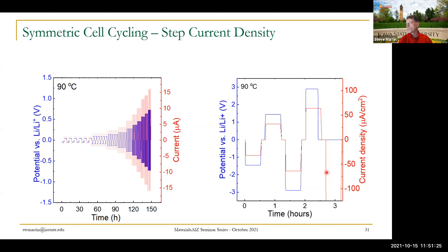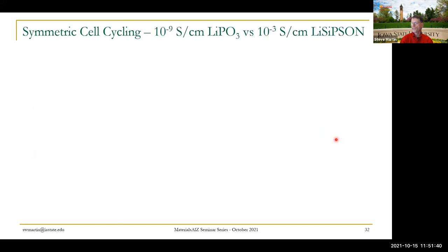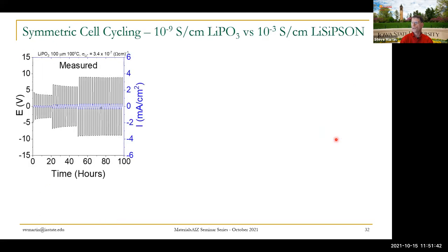The current, of course, is not changing, but the voltage, right? This is now metallic lithium through the glass. These dendrites shorted out the glass. So it took a lot, but we eventually shorted it out. I think that's in the next one, just to show you. Now, let me wrap up with this slide.